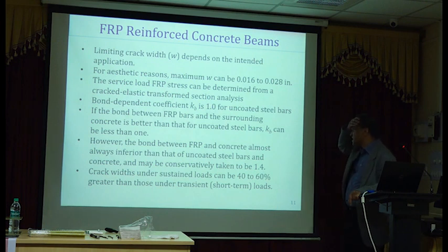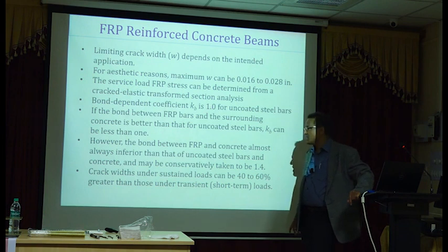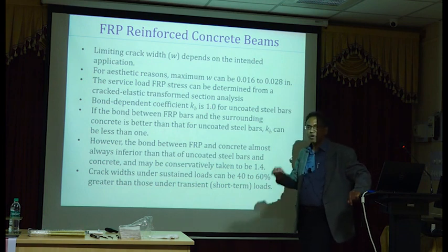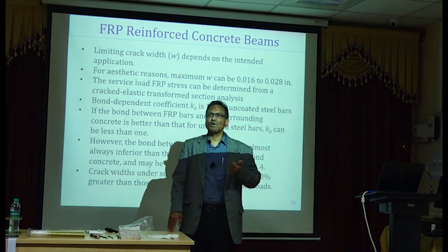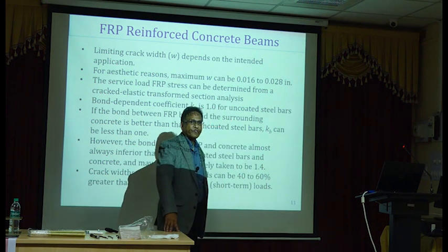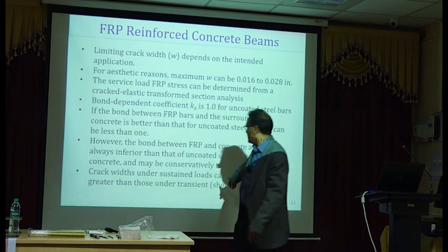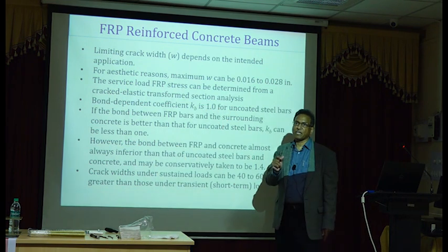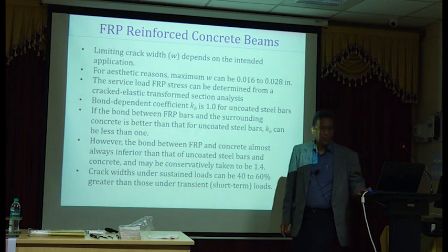Crack widths under sustained loads can be 40 to 60% larger than under short term or transient loads. That's something I think somebody was talking about, sustained loading and cracking. One of you, a PhD student. So if you have sustained loading, the crack widths will always be larger, for sure.